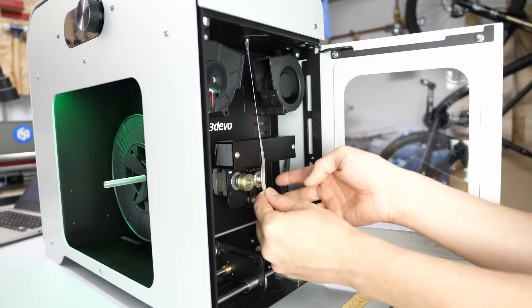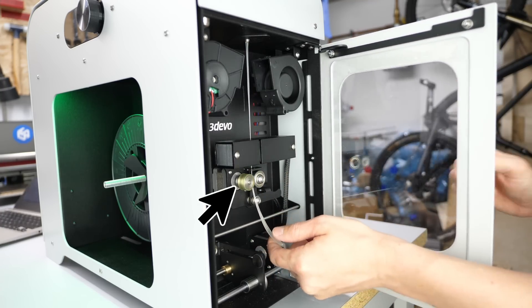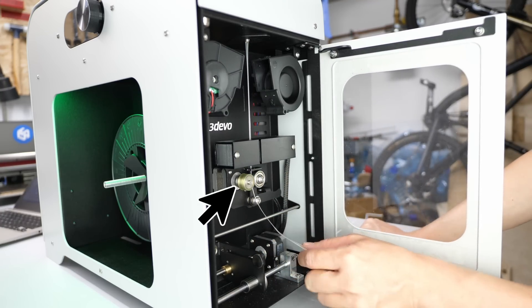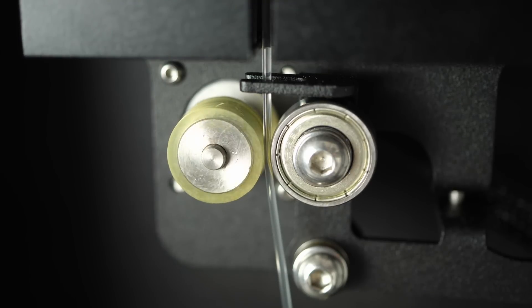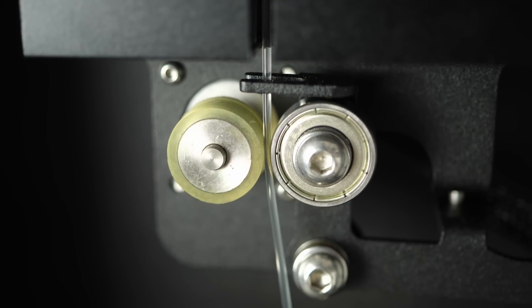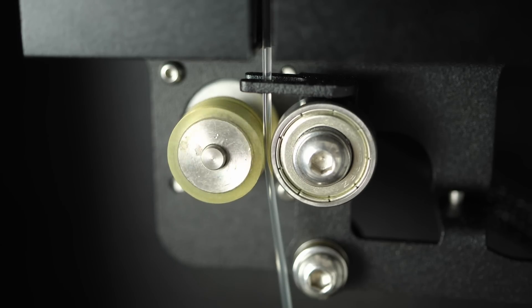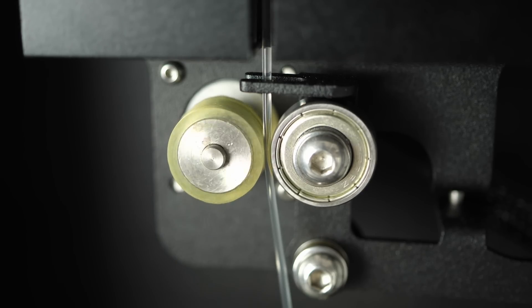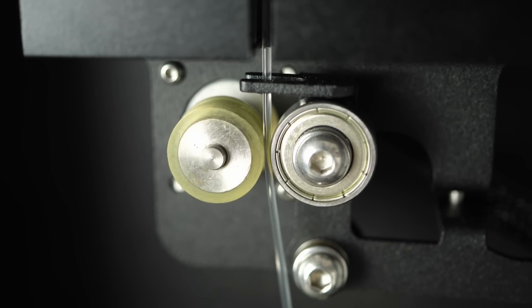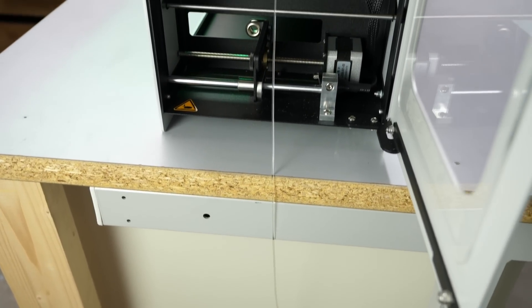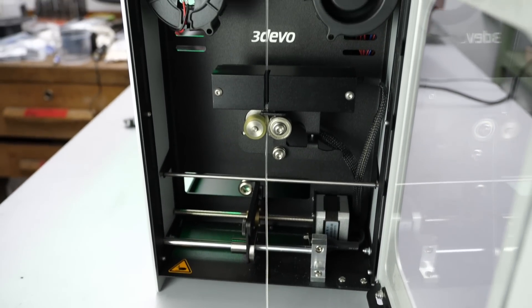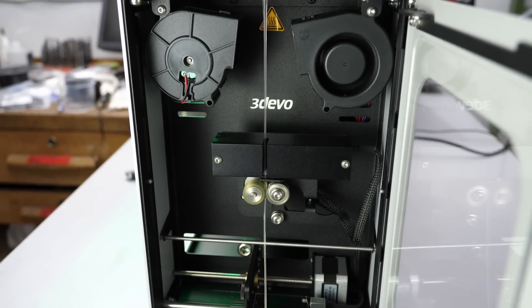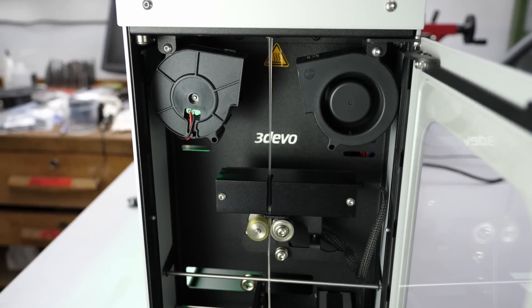The reason for that is that 3D printing filament is usually not directly extruded into shape, but a puller wheel is actually dragging the material to its final diameter, adjusting the speed at which it's pulling depending on the diameter measured by an optical sensor. This way the machine can compensate for not perfectly equal extrusion and die swell. To make sure that the filament doesn't get squished from the puller and to make sure that it doesn't just droop down after it leaves the nozzle, it gets cooled by two cooling fans that blow on it.